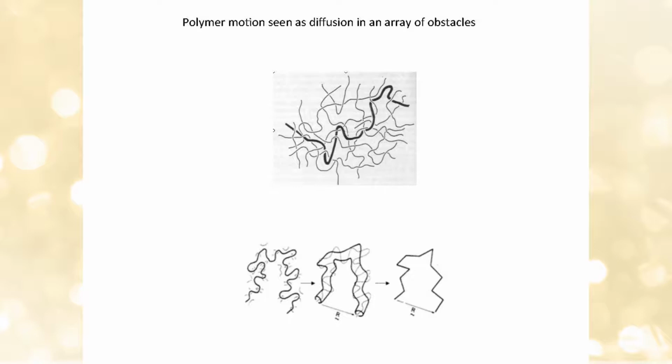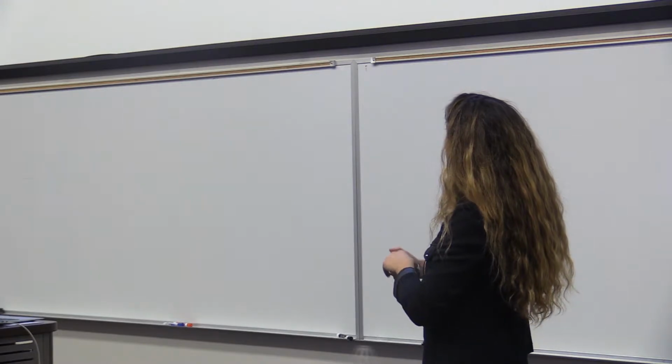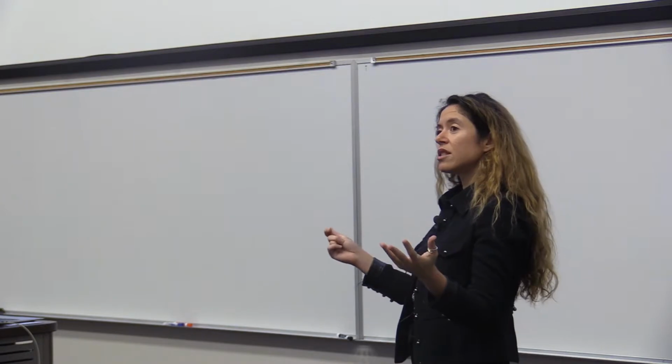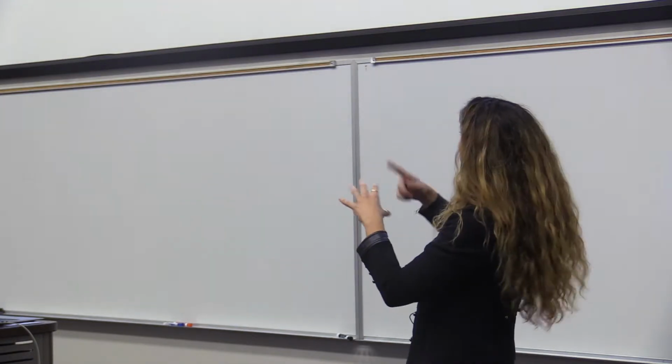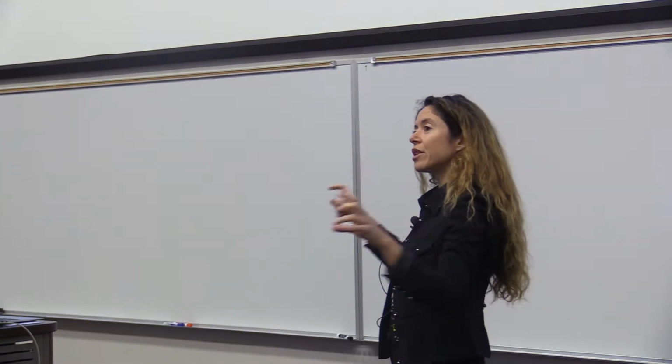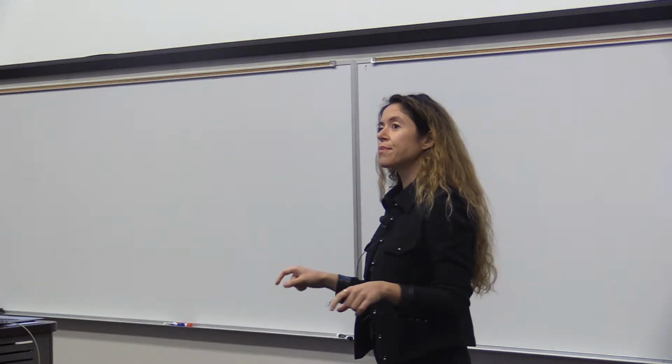So when we study polymer properties, one can see the effect of entanglement arising. You have many chains, all of them entangled with each other like spaghetti, and you want to understand how they move and how that affects their mechanical properties. The idea is that if you imagine one chain, the one highlighted there, tries to move, and suppose the other ones are fixed around it, then it cannot move anywhere it wants, but it has to diffuse within this imaginary tube-like region formed by the surrounding obstacles.